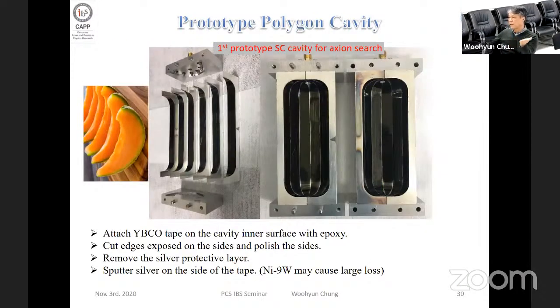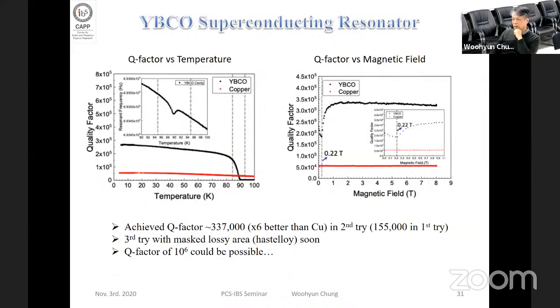I call this the melon cavity because I gave it the melon cut. If you look at the picture, on each piece we put the YBCO tapes like this, and the YBCO surface is exposed in the cavity, and then we put it together and measure. So this is the result. Actually, this is a second try. In the first try, the Q factor went up to 150,000. Our surface was miserable, so we made a second try with a better surface, and our Q factor went up to more than 300,000. The amazing thing is that you can see a phase transition here, and it goes up and up.